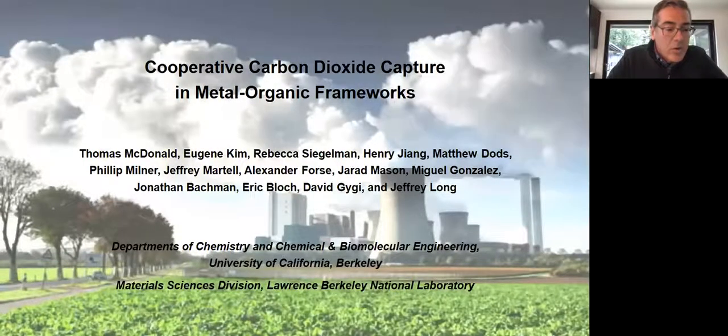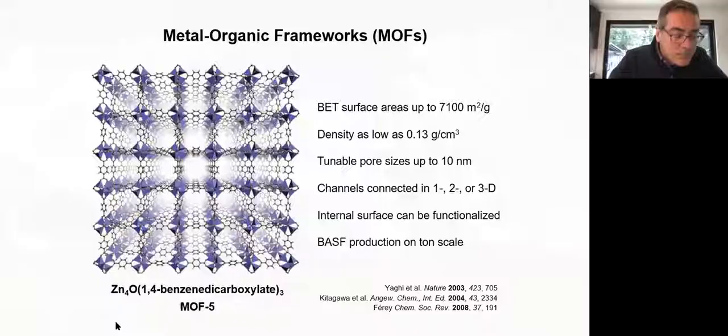And the materials that we work on are metal organic frameworks. And these are, to us, sort of designer zeolites, where you can use the power of synthetic chemistry to adjust the pore size, the pore geometry, the pore shape, or the pore dimensions, and also the surface functionality of the material. And it's that chemical tunability combined with record high surface areas that make MOFs powerful for separation, such as CO2 capture.